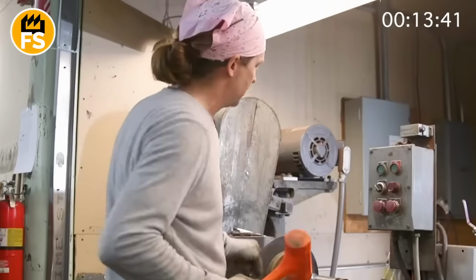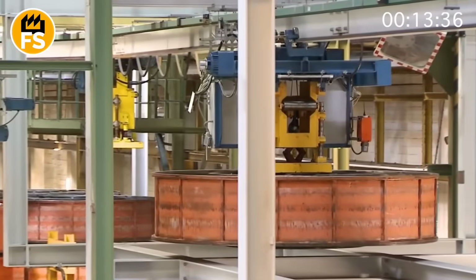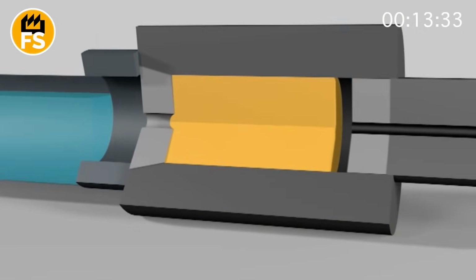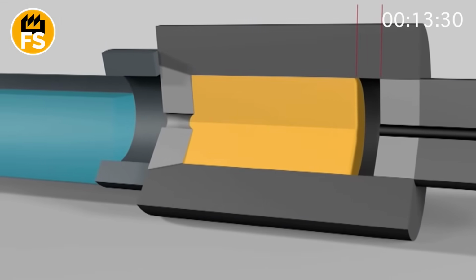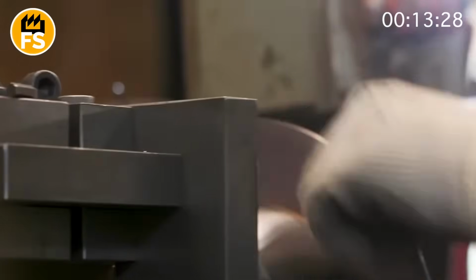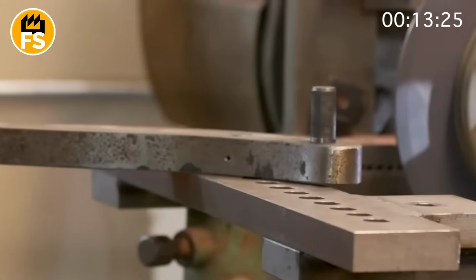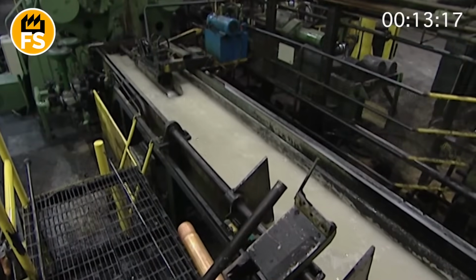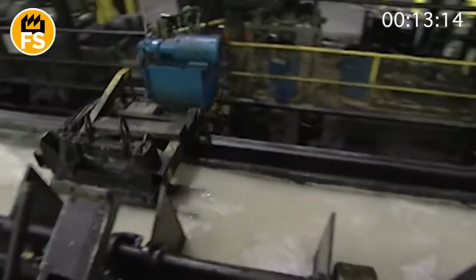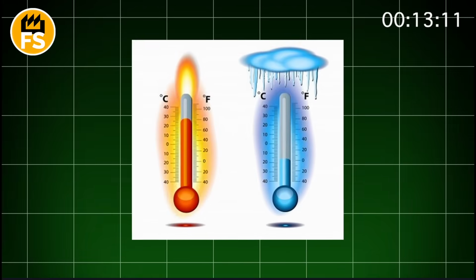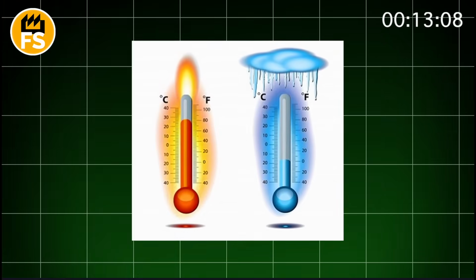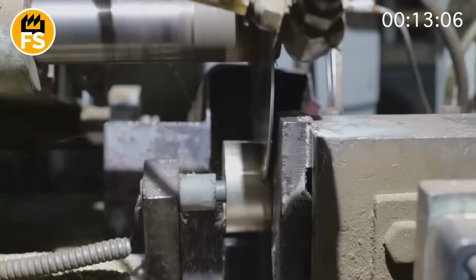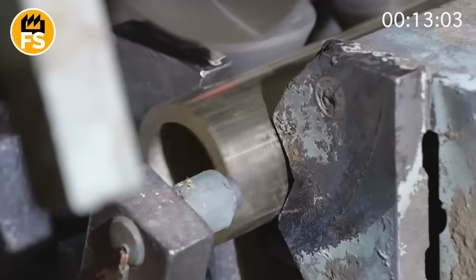Each pipe undergoes automatic inspection. Laser scanners search for microcracks and defects, and special robots select samples for additional testing. After being drawn from the red-hot die, the copper pipe is still hot, flexible, and prone to deformation. To quickly give it stability, the pipes are automatically directed onto a conveyor, leading to special cooling pools. Inside is cold water, which creates clouds of steam upon contact with the incandescent metal. This sharp temperature drop locks the pipe's shape, preventing it from bending or losing its geometry. Cooling takes only a few tens of seconds, but is crucial for quality.